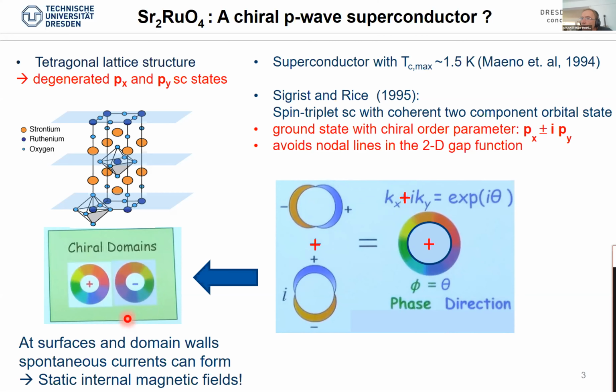So important for μSR, and for any technique to measure time reversal symmetry breaking, is what Vadim also mentioned: that at surfaces or impurities or at these domain walls, spontaneous currents can form, and this will give rise to static internal magnetic fields, which we detect by μSR.